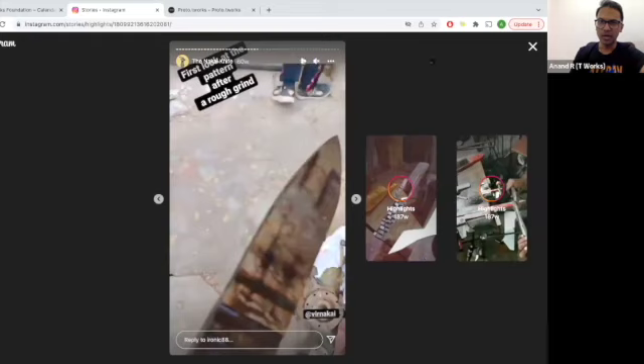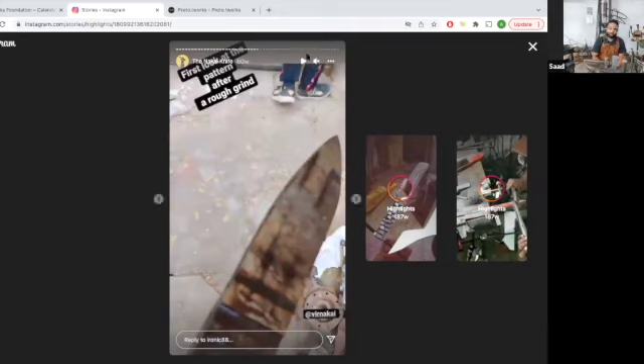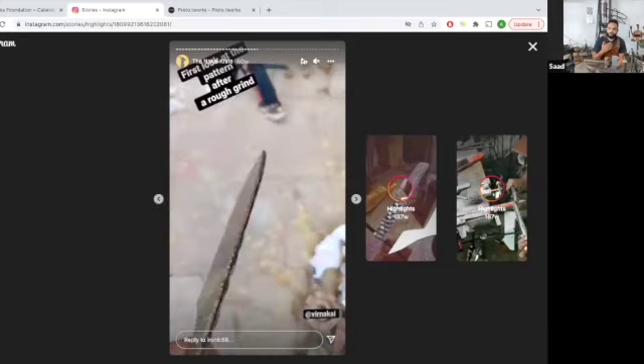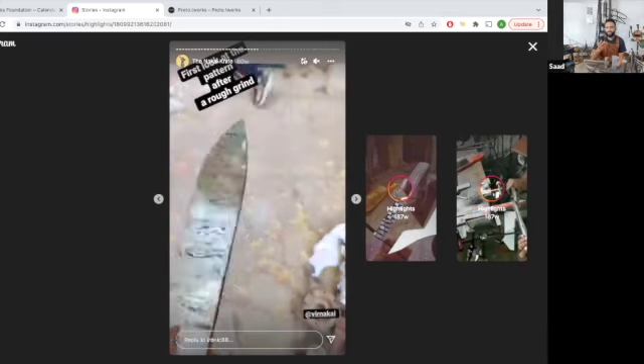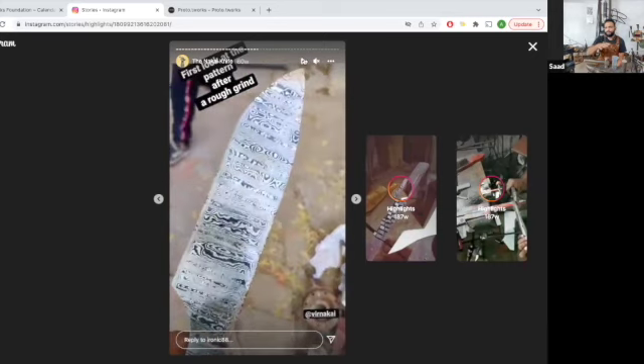Do you have control on the temperature of your forge? No. So the way you can guess temperature is by the color of the steel. Usually when you go to a blacksmith, I don't know whether movies portray it properly, but blacksmith workshops, they prefer to keep it dark because they gauge the temperature of the steel by the color. So if it is dull red, it is a certain color. If it's bright red, it's a certain color. If it starts turning yellow, it's a certain temperature, not a certain color. Obviously, it's a certain color, but yeah.